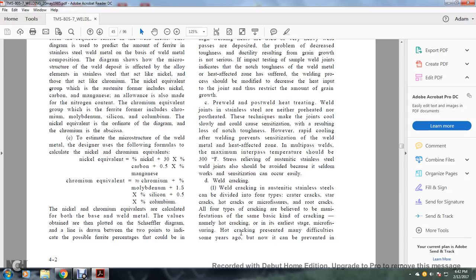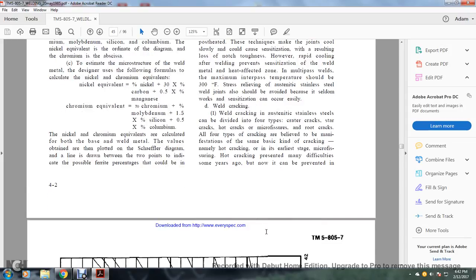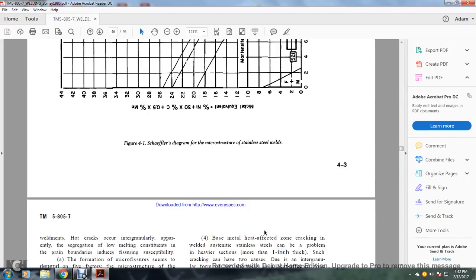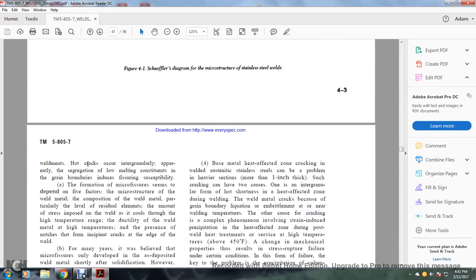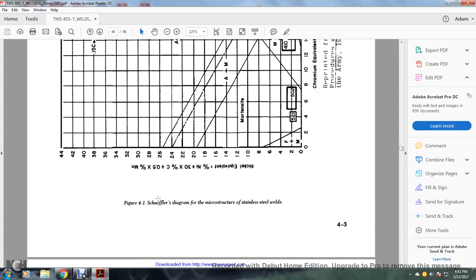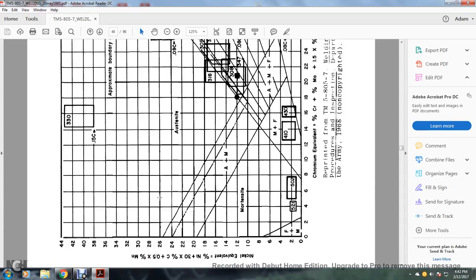Hot cracking presented many difficulties some years ago, but now it can be prevented in weldments. Hot cracks occur intergranularly, apparently with the segregation of low melting point constituents in the grain boundaries, increasing fissure susceptibility. Figure 4.1, Schaeffler diagram: microstructure of stainless steel weld.